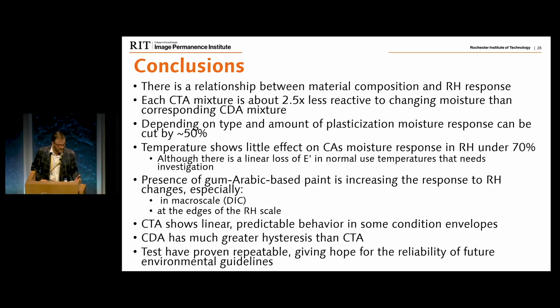So to conclude, we have definitely found out some relationships between the material composition and the RH response. We found out about the differences between diacetate and triacetate response. We know that type and amount of plasticization can affect that moisture response. There is very little effect of the cellulose acetates. However, when you look at the Tg curves, modulus curves in the Tg tests between -20 and +25 degrees Celsius, there is about 20% drop. So we will definitely have to look into that. How safe is that change?